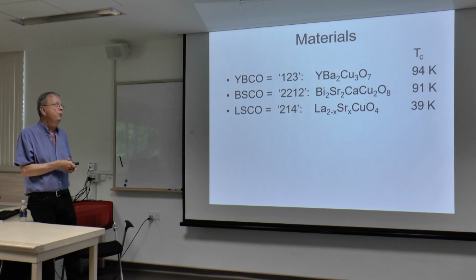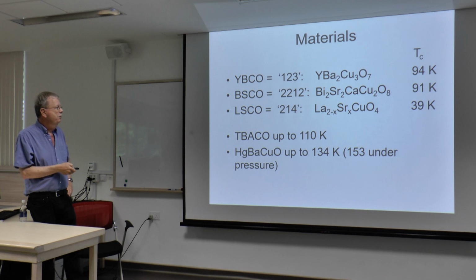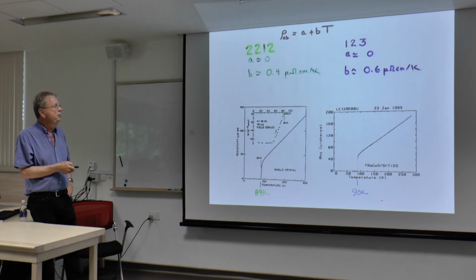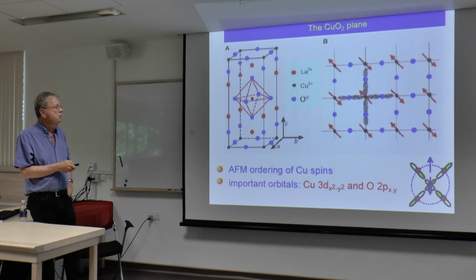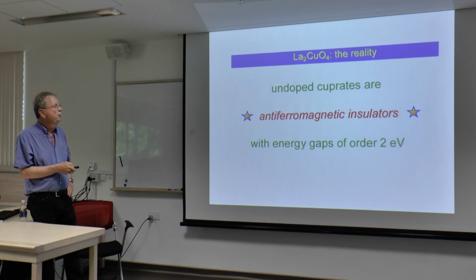Again, people prefer the better quality sample, again using strontium versus barium. This is the record holder. We talked about that. That's some early data. Resistivity is linear above here, up to a very high temperature. Here's the picture again. They're antiferromagnetic insulators, so there's a big gap, so you need to dope them with something.